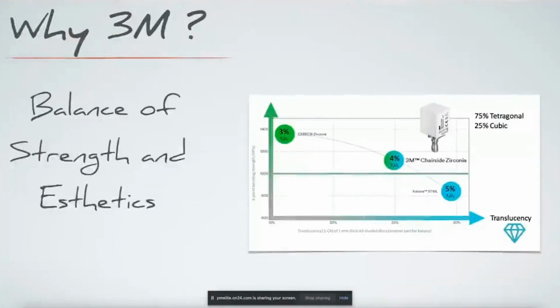So if we look at this chart, and we kind of see where things are, on the far left, again, we're back to that kind of 1400, 1300 megapascal strength of BruxZir zirconia, that really opaque zirconia. But again, not very aesthetic. We can go to the other side. We can start approaching Katana, which is 5%. And that's a really aesthetic material, I think on par with some of the low translucency or even medium translucency glass ceramics like Emax. But I'm not really getting the strength that I want. And depending on what you read in terms of Katana's materials, sometimes this is going to be dependent on thickness recommended for bonding, right?